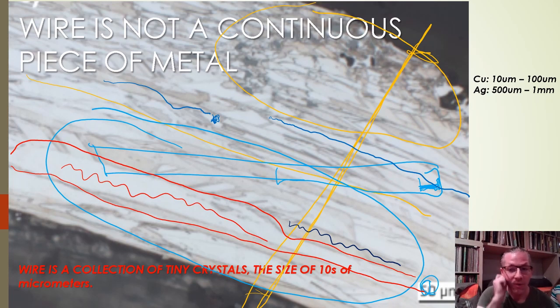However, if you have an AC signal, then that's a problem, because if your electrons here spend some time before jumping to the next domain, by the time they decide to jump, the signal already changes, and your electrons are supposed to flow the other way around. So this jumpy travel of the electrons creates a rectification effect. So all of these jumps between single crystal domains rectify partially the electron flow, and that's why the AC signal is affected by the structure of the crystal.